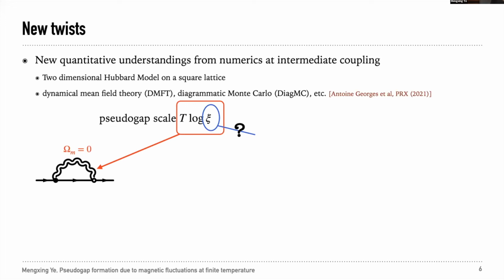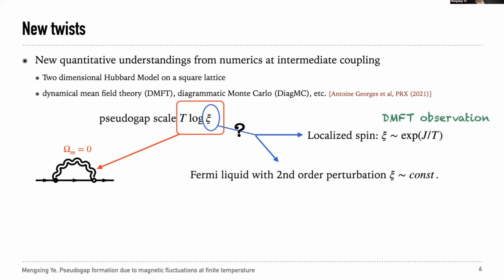However, the question is what determines this spin correlation length? If, to be consistent, we consider this Fermi liquid picture within second order, it turns out that the spin correlation length is a constant. However, the DMFT study shows that the spin correlation length is proportional to the exponential of inverse temperature, which is a feature that can be captured by the nonlinear sigma model if we consider a localized spin model. However, as I mentioned, we are considering this Fermi liquid interacting with the magnetic fluctuations. So the question is, can we start from this Fermi liquid and get this spin correlation length that can be captured by the nonlinear sigma model? This set our motivation for this study.